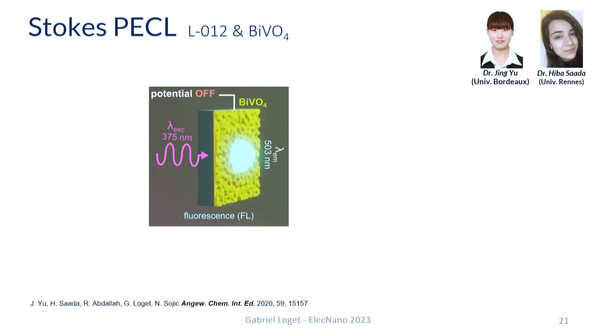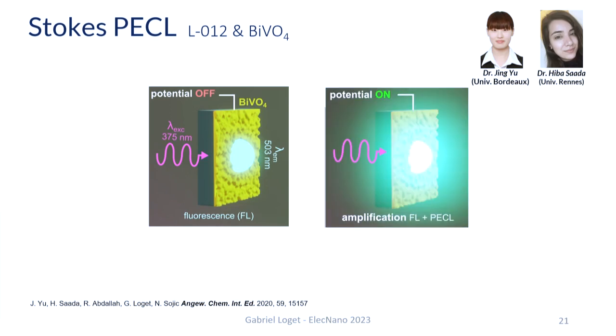Here we are working in backside illumination configuration. We illuminate through the glass slide, the conducting substrate that we use for depositing the bismuth vanadate. Because this electrode is pseudo-transparent, a part of the photons are going to reach the electrolyte, and L012 is going to luminesce. And this is what happens at open circuit condition. But when we apply the potential, PECL is going to occur simultaneously, and then we'll have fluorescence plus PECL, and this will lead to amplification of the luminescent signal. So here we have a Stokes-type PECL system where UV light, a high energy optical input, is converted into an output of a lower energy.